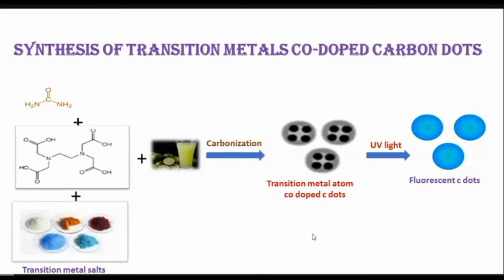So the strategy is given here. The precursors undergo carbonization when irradiated in the microwave. Thus, we get the transition metal co-doped carbon dots, which under UV light show fluorescence.